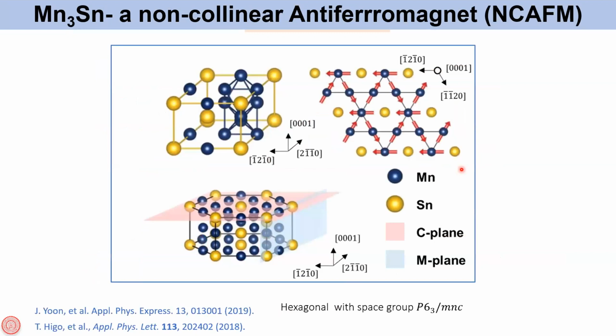If you look at the crystal structure of Mn3Sn, it has this Kagome lattice in the C plane, and these are the manganese spins shown in red. You can see that they are at 120 degrees to each other, and this leads to a net zero magnetic moment, but they are not collinear. So it has this Kagome kind of crystal structure. In fact, the previous speaker, Professor Fukami, is an expert in Mn3Sn, although today he presented work different from that, but he has done some groundbreaking work in this material as well.